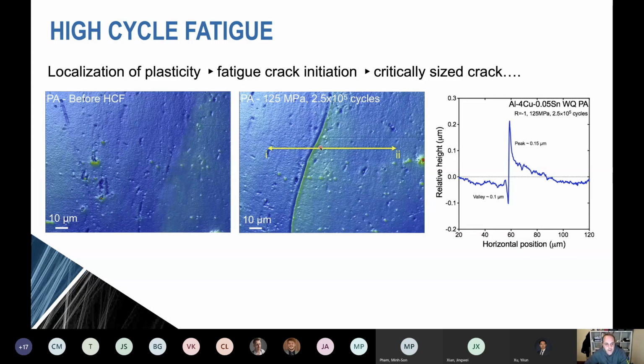Now, in fatigue, and I know certainly at Imperial you have many experts working in fatigue, there are many processes, and they all matter. You have cyclic plasticity, you have the development of a localization of plasticity, fatigue crack initiation, the formation of a critically sized crack followed by fatigue crack growth and final failure. All of the stages matter, but for different types of fatigue loading, one or the other can dominate the lifetime. And in high cycle fatigue, it's really the time required to generate a critically sized crack that dominates most of the lifetime, certainly in lab-sized materials. And so this process of plasticity localization in the precipitate-free zones is a really important process, and actually we'd like to delay it.